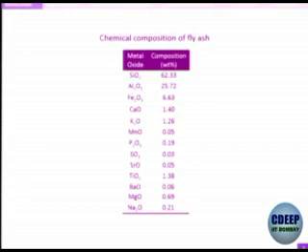So silica dissolution is something we will be talking about, which gives activity to silica. Clear? That time I will talk about this issue. So silica gets dissolved in hydroxide. Look at this. You have sodium oxide, Na2O, and K2O, potassium oxide. The moment these two oxides come in contact with water, they create hydroxides. Now these hydroxides have a tendency to eat up silica. Etching of silica, that part I want to show them because he has raised this issue. And then the silica particle becomes reactive. Then only the reaction with calcium hydroxide will take place. Clear? Not before that. So silica, by virtue of being a passive material, if it is in crystalline form, is a good material for filling purpose, not for cementitious purpose.